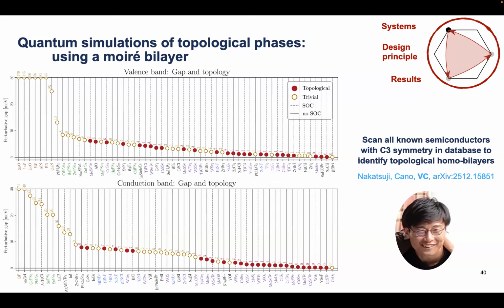And we've actually done a continuum model and tried to add lattice relaxation. Interlayer relaxation is effectively included because we run DFT at different stacking points, and for each of these stacking points we allow for relaxation in the Z direction. So intralayer is not included, and intralayer relaxation sets in between 2 and 3 degrees. So below 2 to 3 degrees, you cannot trust that data, only because a single harmonic in the potential is sufficient. Yes, exactly.